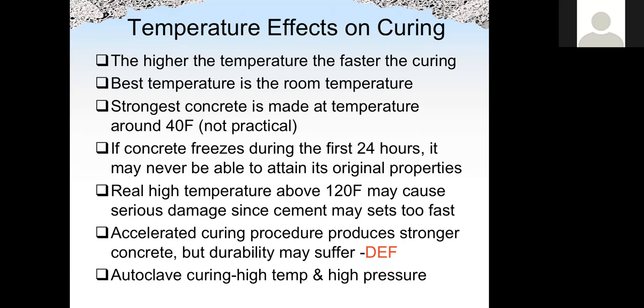If the concrete freezes during the first 24 hours or the first week, it may never be able to attain its original properties. So we need to keep the concrete above freezing temperature at early age at least. If the temperature is very high, about 120 degrees Fahrenheit, that may also cause damage, okay? Because the concrete may set too fast. And also a potential problem, we call that DEF.